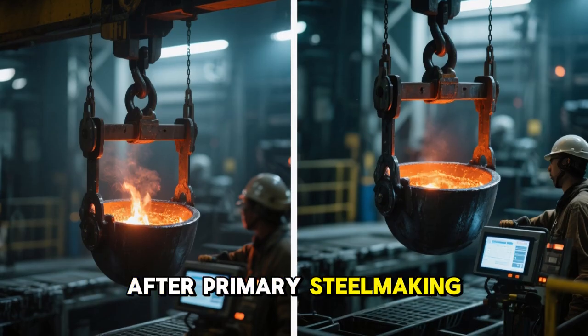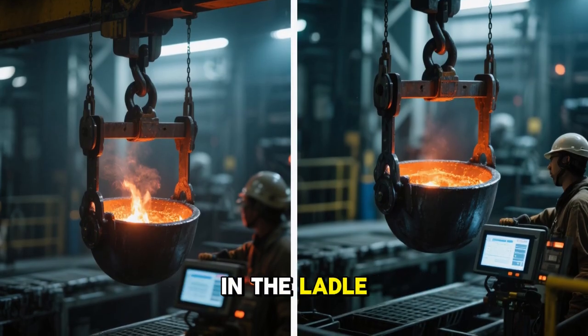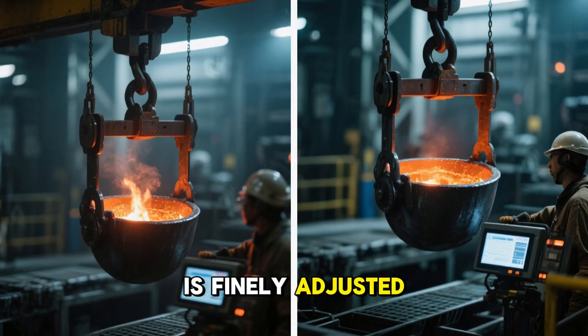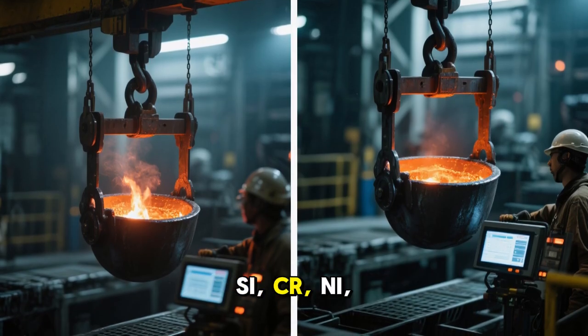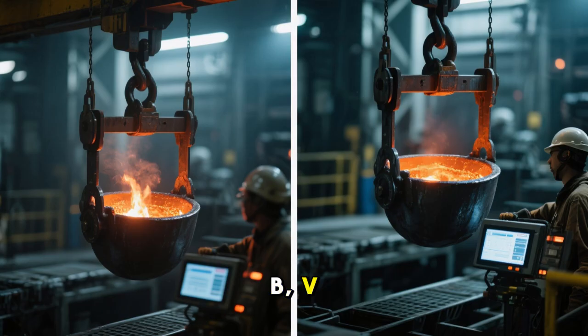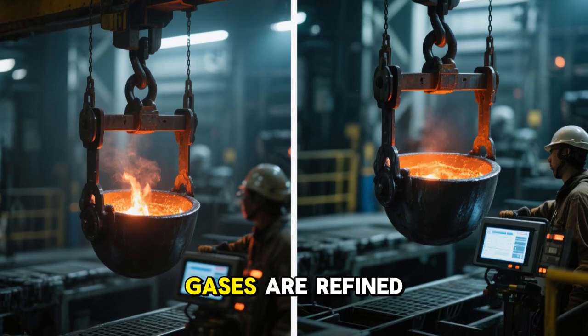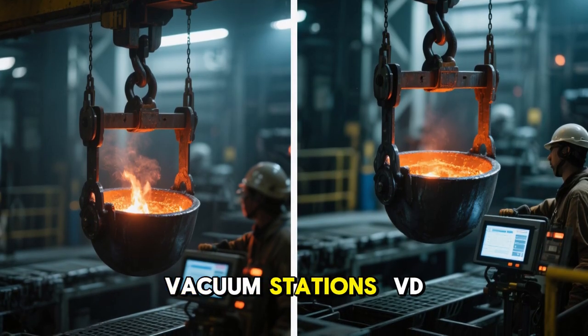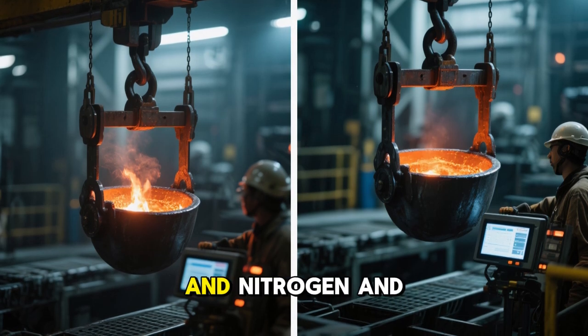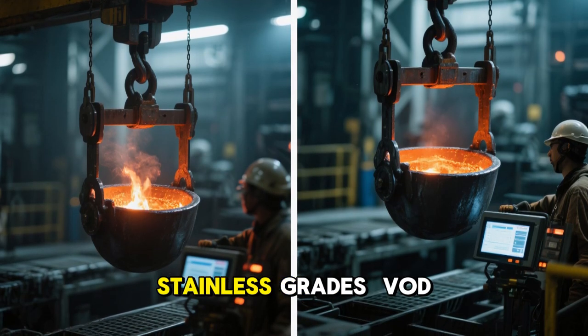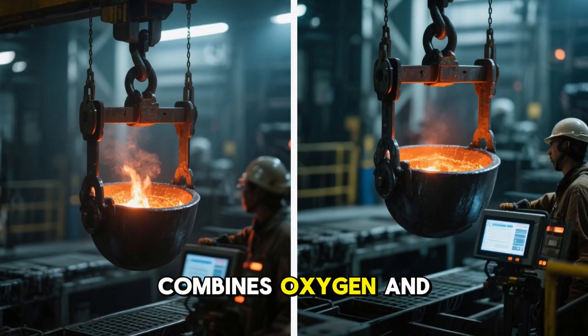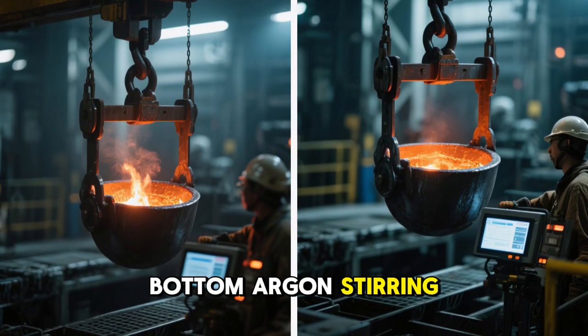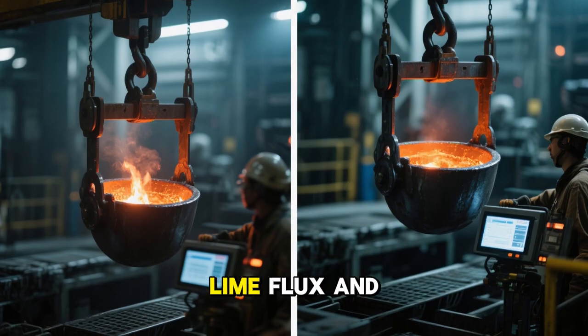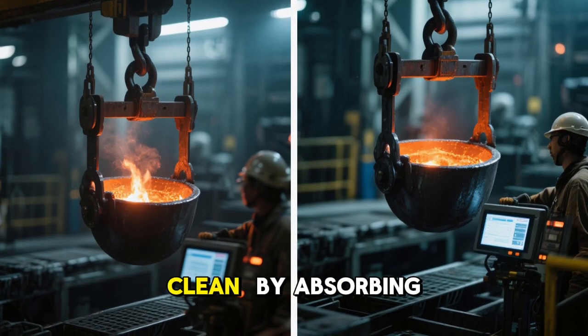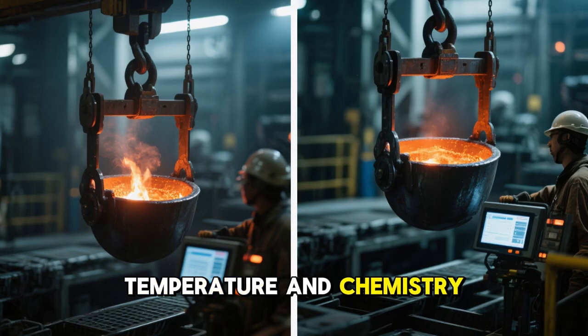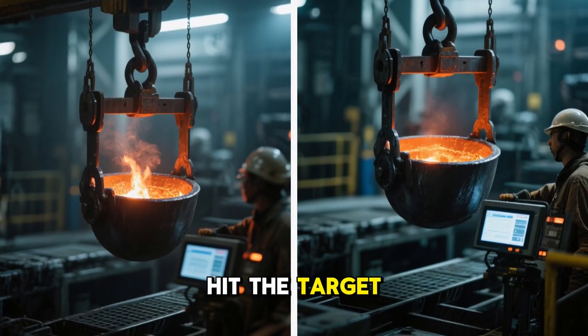After primary steelmaking, the heat goes to secondary metallurgy in the ladle. Here the composition is finely adjusted, alloying with Mn, Si, Cr, Ni, Mo, Nb, Ti, V, Al, and inclusions and dissolved gases are refined. Vacuum stations, VD, VOD, remove hydrogen and nitrogen and allow low carbon levels in stainless grades. VOD combines oxygen and vacuum. Bottom argon stirring promotes thermal and chemical homogeneity. Lime flux and synthetic slags clean by absorbing inclusions. Temperature and chemistry are monitored in real time to hit the target grade.